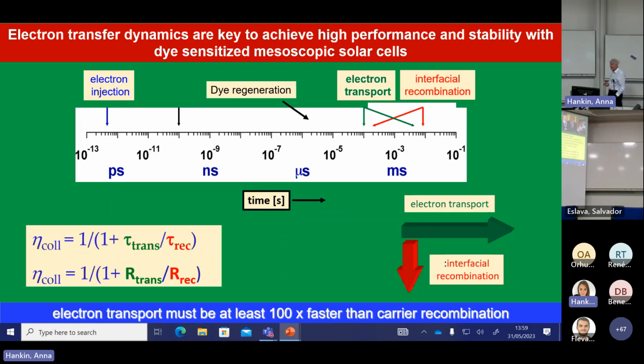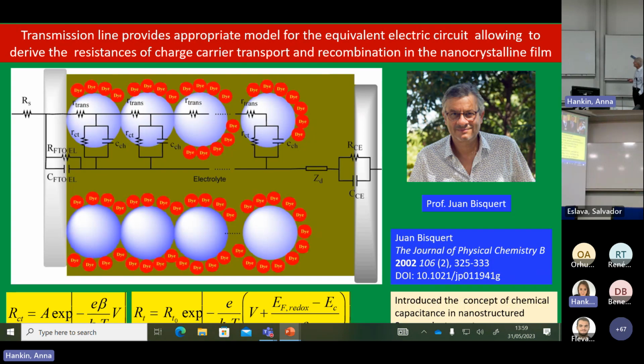And so that's another critical point. You inject electrons, you regenerate the dye. However, what happens to these charges? They still can recombine across the interface. And so how fast is the recombination and transport? That can be measured by impedance spectroscopy. And one bit that helps a great deal is to model this with the transmission line. So we can get these two lifetimes or resistances out easily from impedance studies.